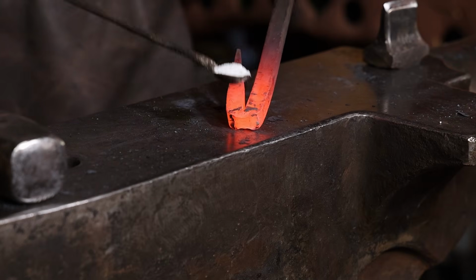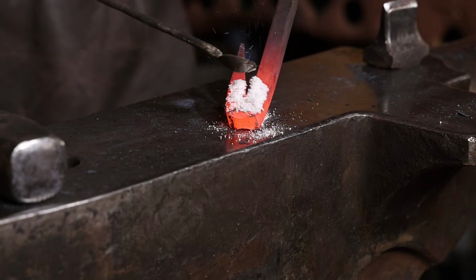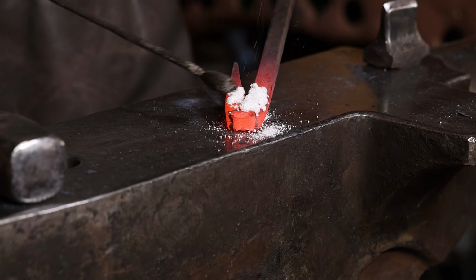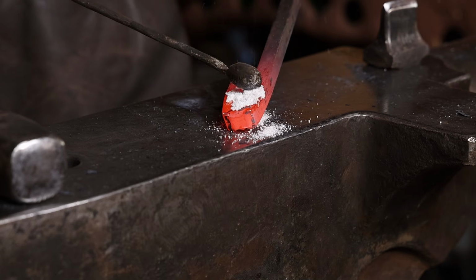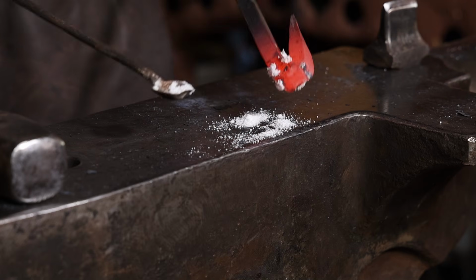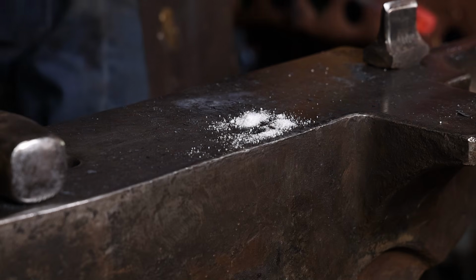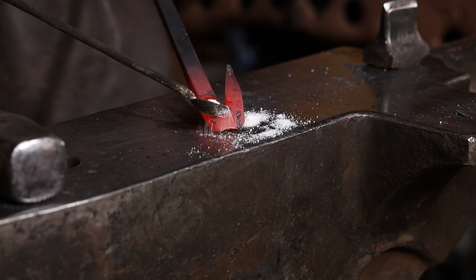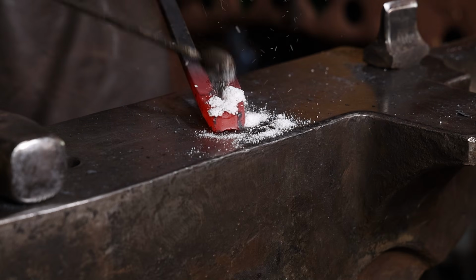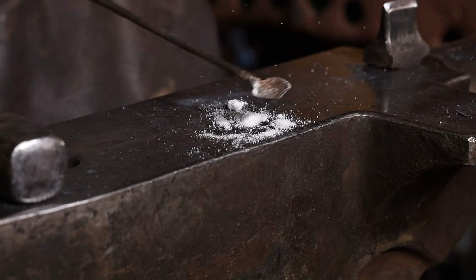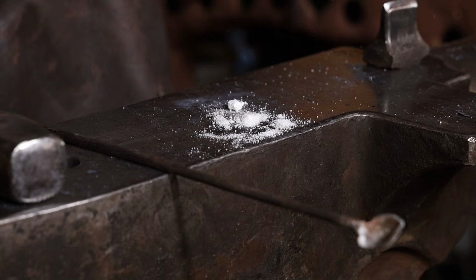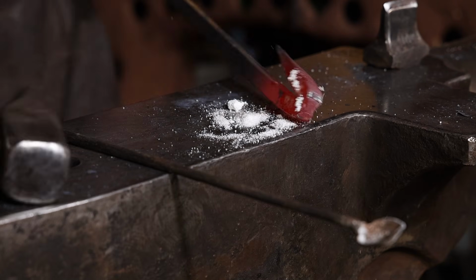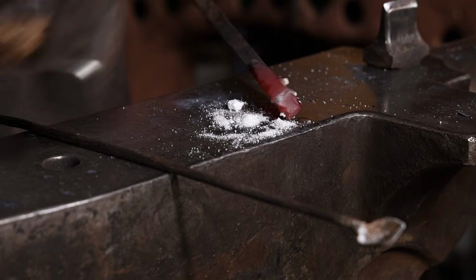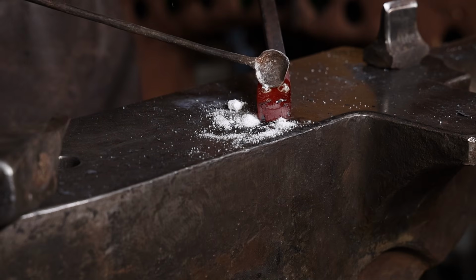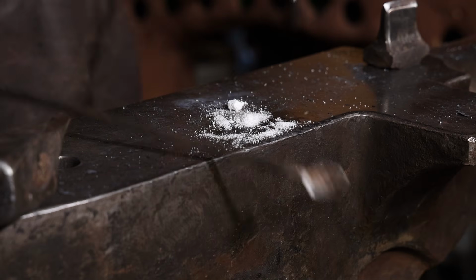We'll go ahead and flux that. The flux on the surface doesn't really matter. What you want is it to get down in, and I just put enough on there to make sure it flows down into the joint. Using mountains of flux doesn't help any. You just need enough to coat the inside of that joint a little bit. Now I'm only going to weld that last inch.